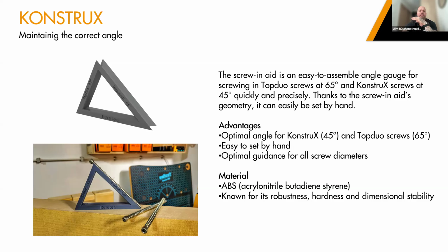If you ever try to set a screw straight at an angle, even with a jig, it will start dancing around, because just the spiral curl of the thread will move the screw along the top surface and not really push it forward, except if you already apply excessive pressure. With a drill point tip, which is more a milling process than a drilling process, to be honest, you mill a little pocket. You can set the screw at 90 degrees without being already in the grain, and then you can lay it in the ramp and install it by moving forward.